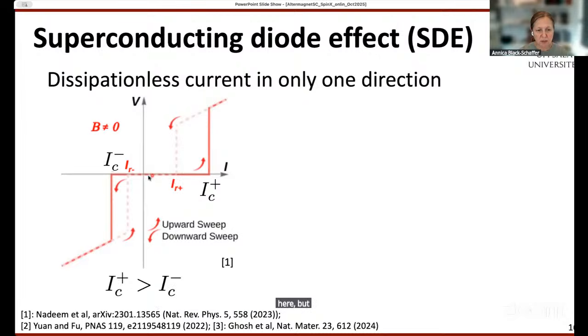In a superconductor, you get a dissipation-less current without applying a voltage. You just have a little bit of a phase bias, or just have current through the structure. And then eventually that, of course, breaks down. When you put enough current in your superconductor, you eventually lose superconductivity, and you generate a finite voltage in the system. So it's illustrated here. And sometimes when you go back, you have some hysteresis here. But what's important is when you go with current in one direction, this critical IC is different from when you go with current in the other direction.